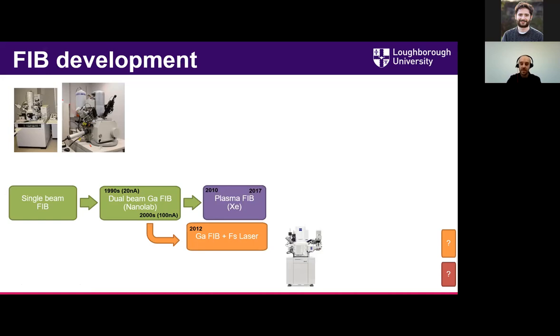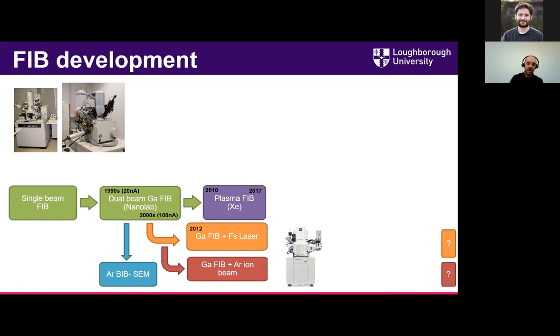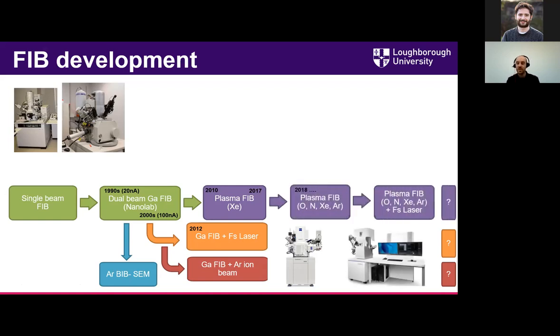And we also started getting laser FIBs, which instead of using a plasma FIB to cut a larger area, use a femtosecond laser. And then people have also started iterating on this, where they've started adding argon ion beams and broad beam mills onto their SEMs. So there's been a whole explosion since the late 2000s, around 2010, of different variants of FIB, even moving towards multi-species FIBs. So we can now implant with or mill with oxygen, nitrogen, xenon, and argon, and even combine femtosecond lasers with multi-species FIBs. So it's a really exciting time to be working on focused ion beam systems.